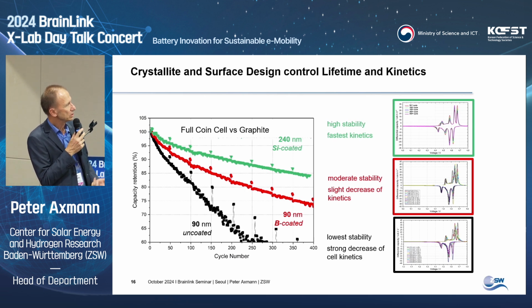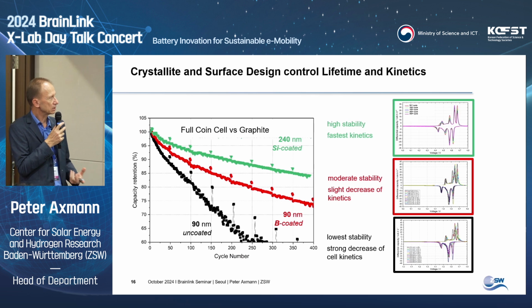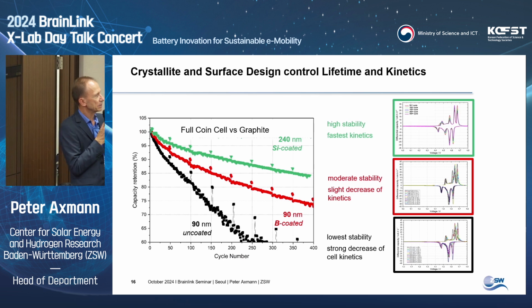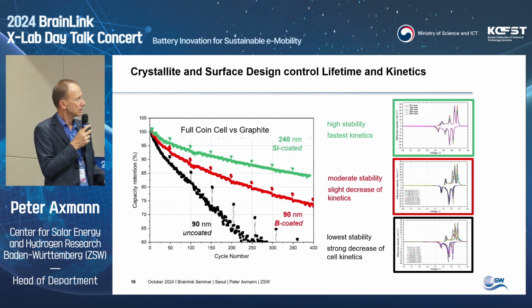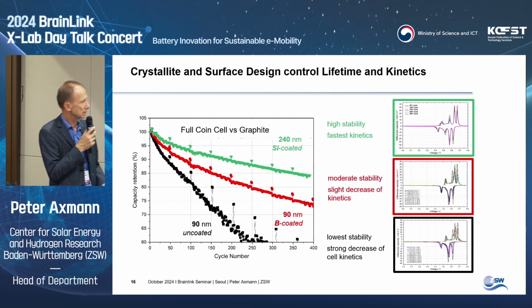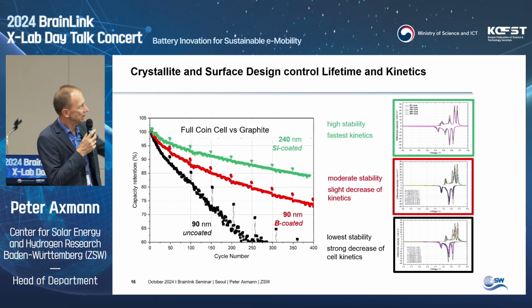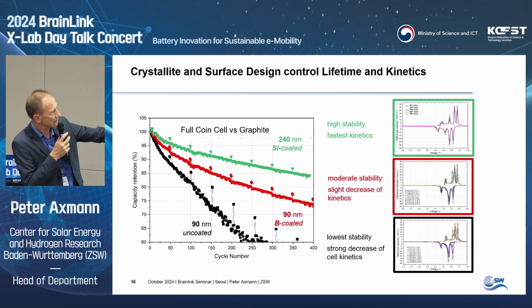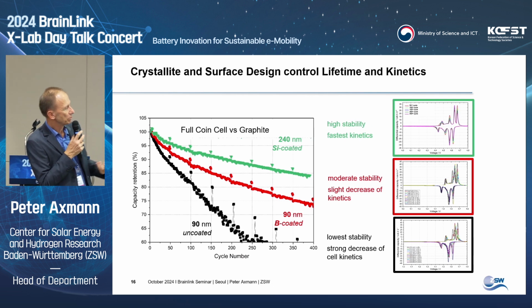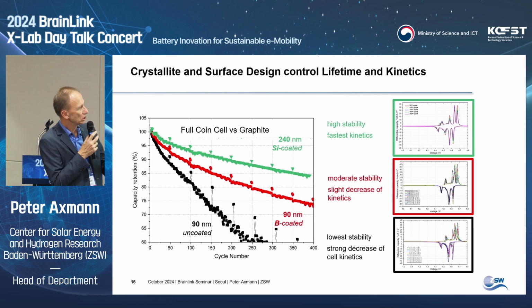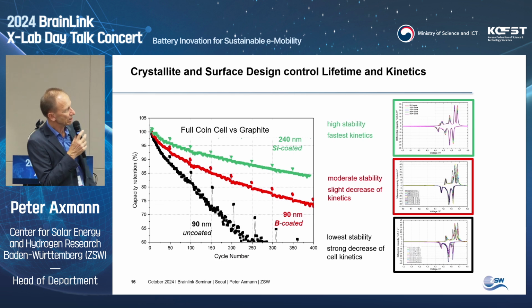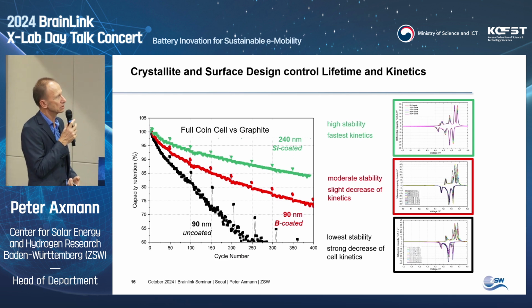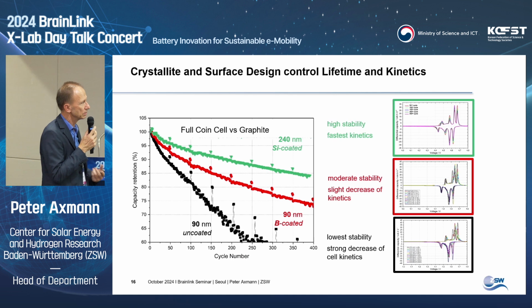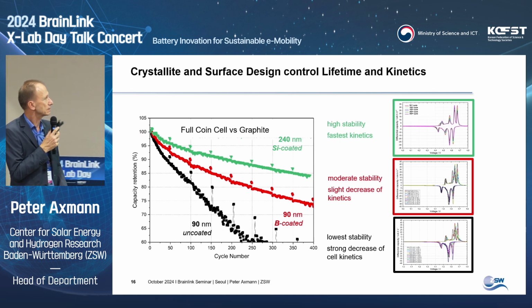And if we then increase the crystallite size from 90 to 240 nanometers, coated with silicon, you can extend the stability even by a factor of 8. And this material is highly stable and has fast discharge kinetics. And as we can see in the capacity derivation curves here on the right-hand side, all changes happening on the positive or negative electrode in terms of aging change the profile. And this is highly pronounced at the lower curve for the strongly aging material, or strongly aging cell. And we see for the stabilized cell, the green part, that nothing changes over several hundred cycles. So we can say neither the cathode nor the anode ages drastically in these optimized cathode materials.